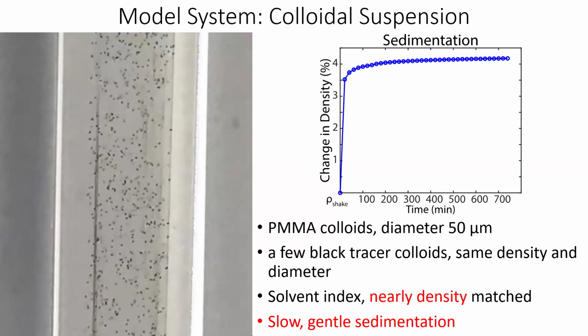We shake it up, and then after 100 minutes, its density has increased by about 4%. And then it continues to densify for the entire time we're able to measure. And this entire time we're able to measure is basically overnight. It's the time between when most everybody leaves the physics department and when the cleaning crew shows up in the morning, and their vibrations ruin our measurements.